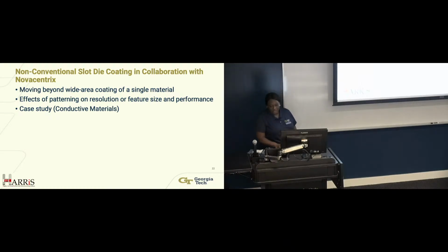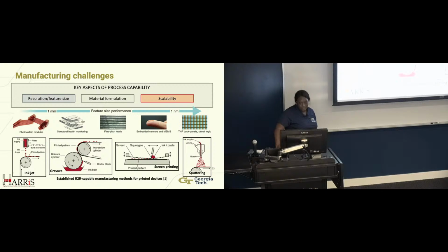I'm going to shift gears quickly and go to the non-conventional slot die coating methods. This work, some of it was done in collaboration with Novacentrix. These materials, some of them are nanocolloidal materials like PEDOT:PSS. Some of them are just inks, for example, silver nanoparticle ink. I showed this cartoon earlier. We have inkjet printing, gravure, screen printing, usually to get the smaller feature sizes.